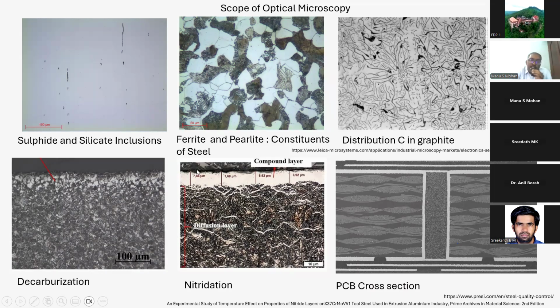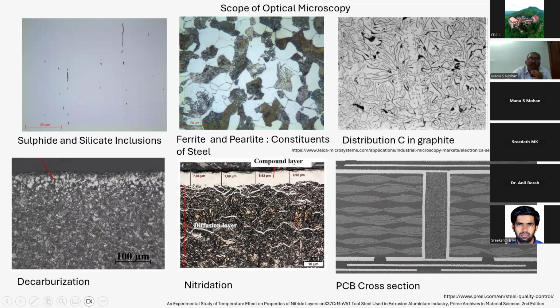Industries are very much interested to know the depth of decarburization, because once it becomes ferrite, it no longer shows bulk properties, as the composition is not the same as the bulk composition. You all know that in metallurgy the main thing is that property depends upon microstructure. So these zones are weak and can cause failure or cracking.